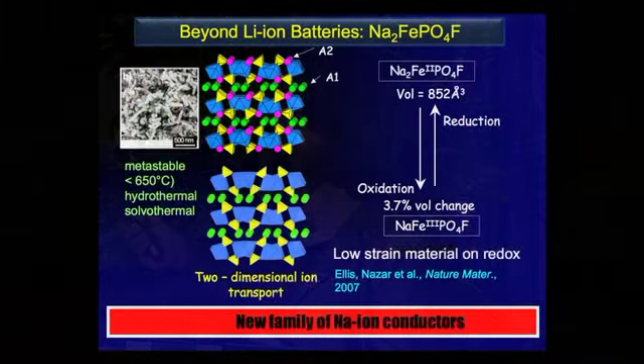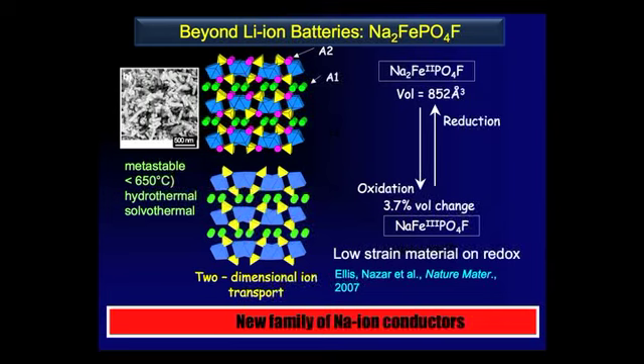So we developed a material which, again, looks a little similar to that lithium iron phosphate. This is a completely different structure. The material forms as this sodium compound. The sodium can be exchanged readily for lithium, so you can also use it for lithium purposes. But the point is that there's two sodium ions in the structure, the pink and the green, so to speak. And on oxidation, just as in the case of lithium iron phosphate, you pull out one of those ions, and so it turns out that the pink ones disappear, and the green ones remain in place, and they effectively hold the structure together, and they stabilize it, they pillar it.